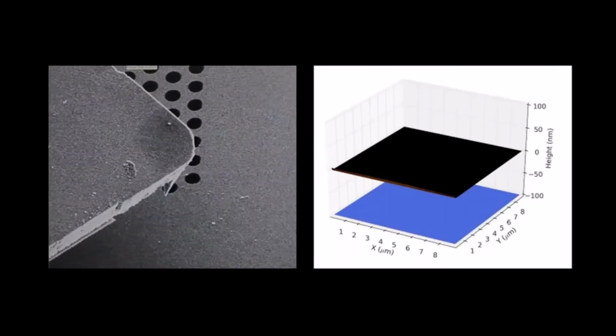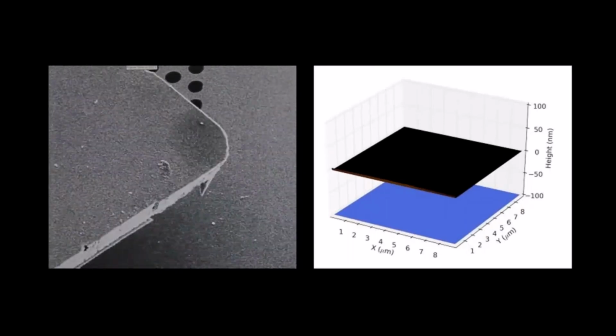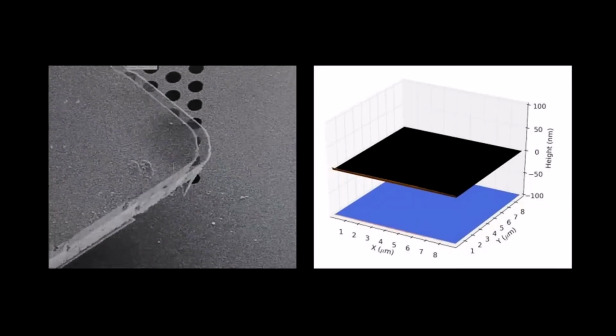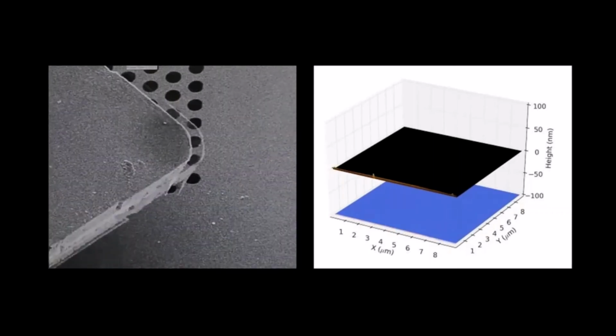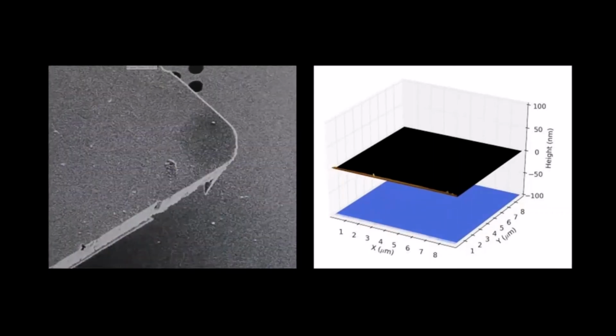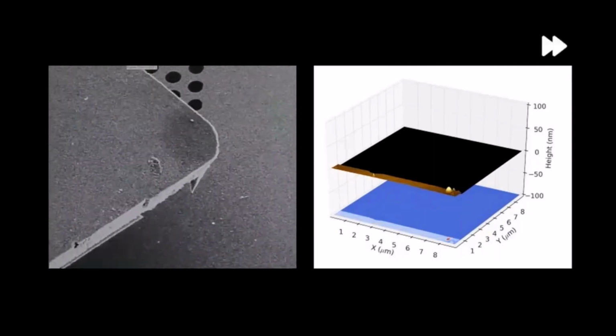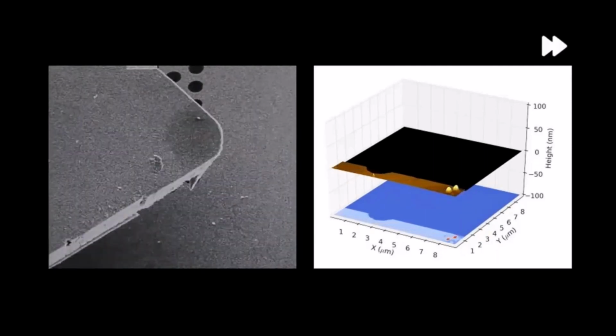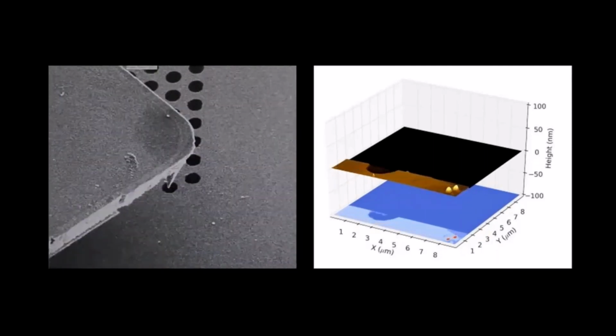So now you see on the left the SEM image, and on the right you see the corresponding AFM data that we are collecting. So we are now measuring, and we are now starting to move over these holes in the silicon nitride substrate that are covered with graphene.